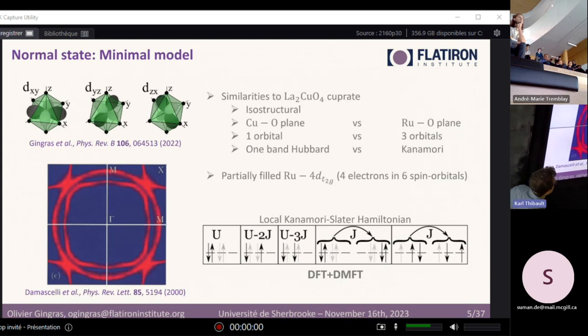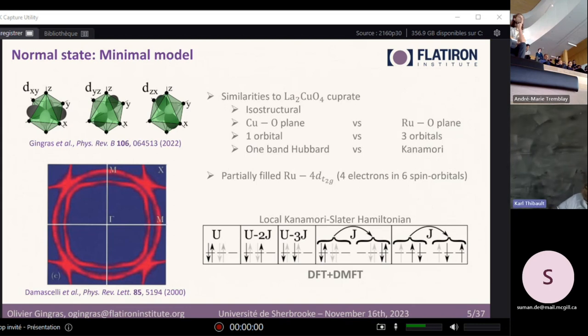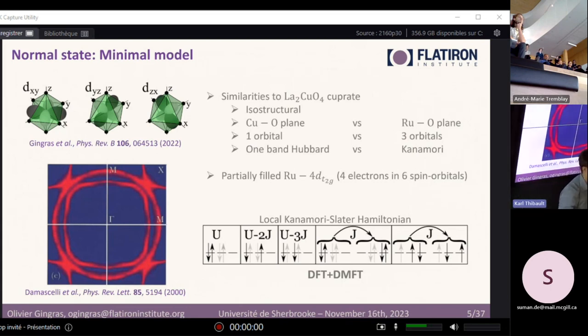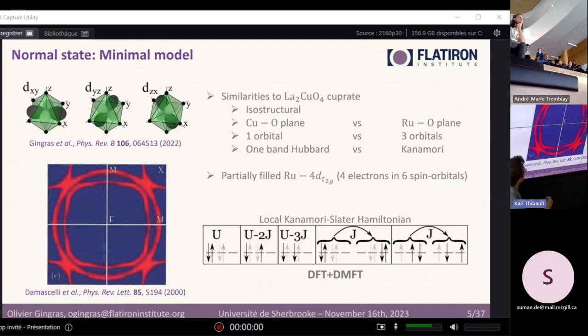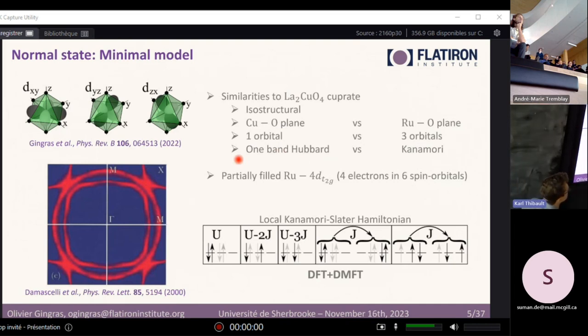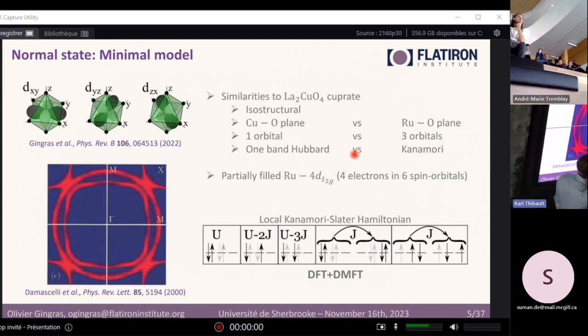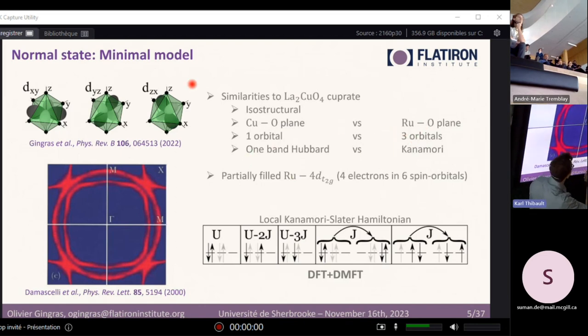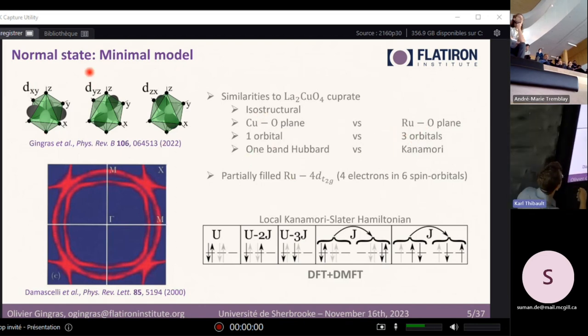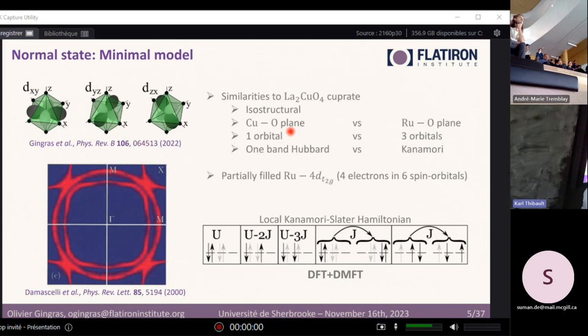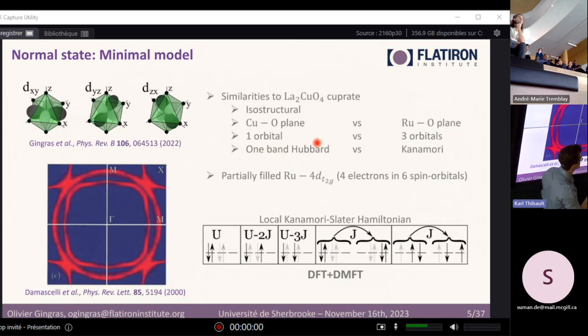But the major difference is that the cuprates are usually discussed in the context of having only a single orbital that is active at the Fermi level. And this is why it's often simulated within the one-band Hubbard model. But in strontium ruthenate, there are three orbitals that are active at the Fermi level, namely the three t2g orbitals shown here, xy, yz, and zx. And so we need a multi-orbital generalization of the Hubbard model to describe the interactions in this material.